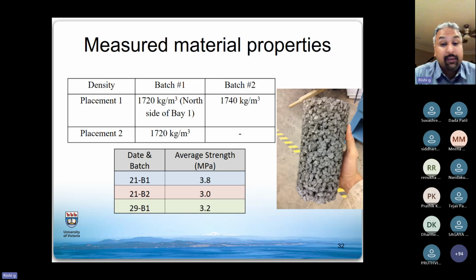Our strength was, as expected, dramatically down, right? So we were down maybe 3-4 MPa of concrete, but that's the reason why we had 6 inches of concrete. One of the potential research areas here: one of the reasons that contributed to the poor strength is there were no standards that prescribed how to make cylinders for porous concrete. I know in India we do cubes. There is a standard procedure to make cubes, how to compact them. We have similar in the Canadian Standards Association and ASTM prescribing how to make cylinders. But how to make cylinders for porous concrete? You cannot do tamping with a rod and so on. So I think part of that was that. If I had to guess, I think we were more like 10 MPa, which is what our industry partner had targeted in this particular case.